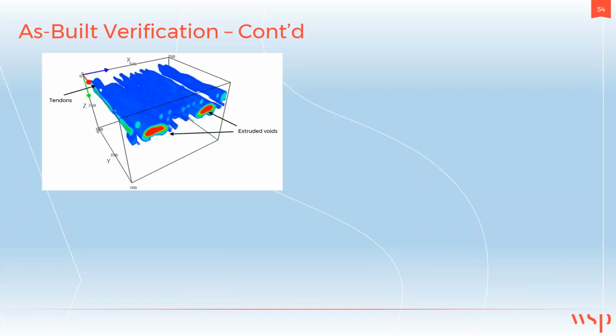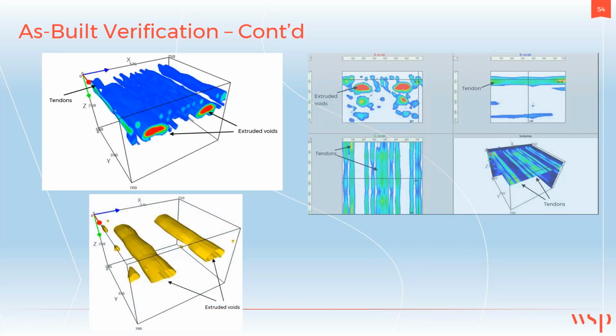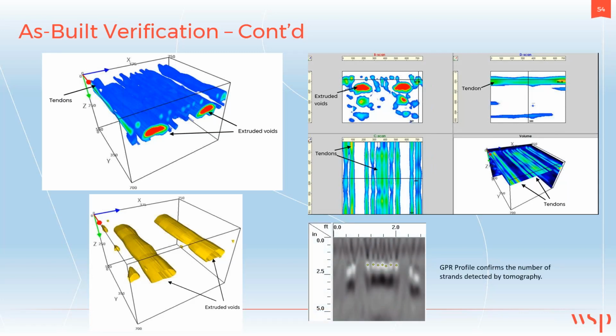A little bit simpler example is this hollow core slab. We can reconstruct the extruded voids and the tendons. Here's the migrated GPR profile, which confirms the results from tomography.